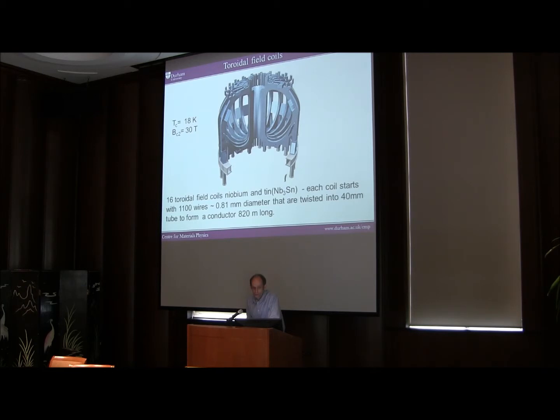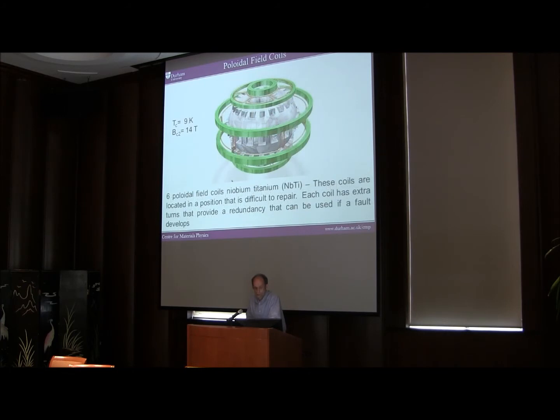So the toroidal coils themselves, they're made out of this niobium tin compound. The superconductors themselves are just under 1 millimetre diameter wires. There's 1,100 of them twisted together to form each coil. 820 metres, almost a kilometre long in total, wound round to form each one of these toroidal coils that go around the core of the device. And similarly for the poloidal field coils, they're made out of a different material. Again, niobium, but this time a niobium titanium material. Again, the European ones will be tested at Durham.